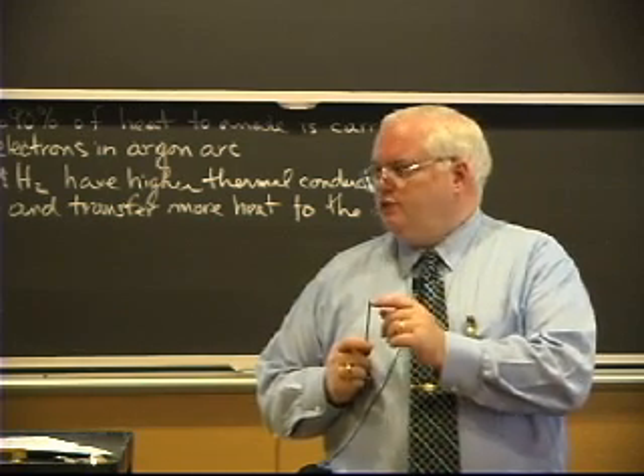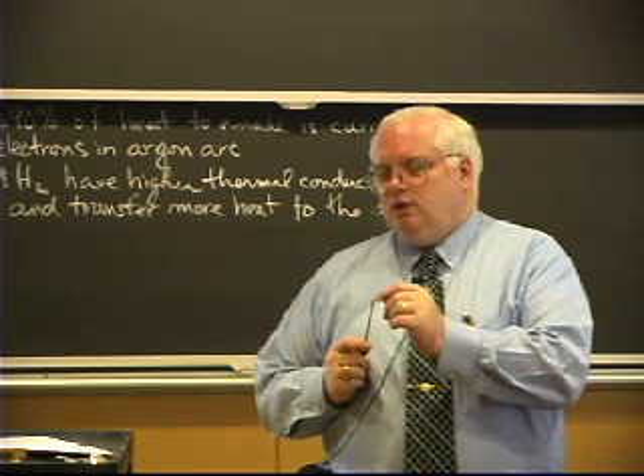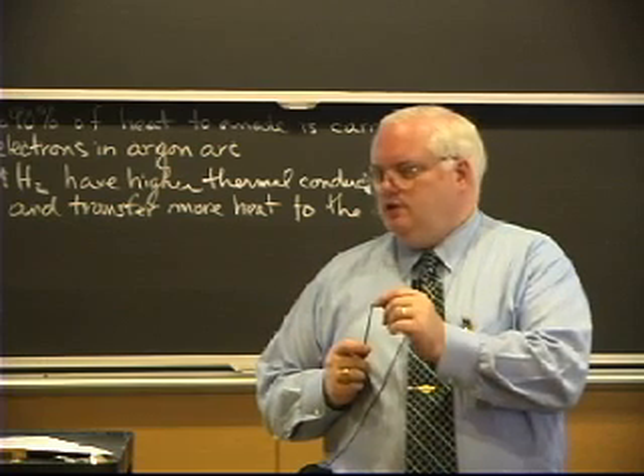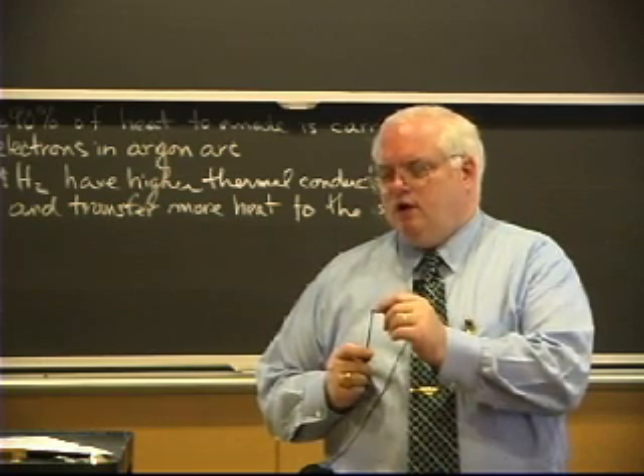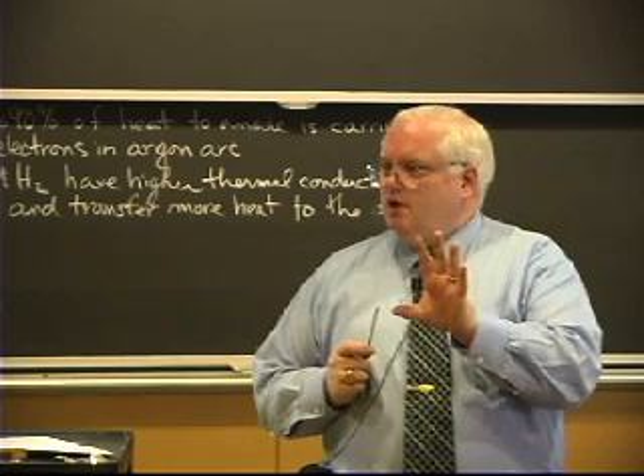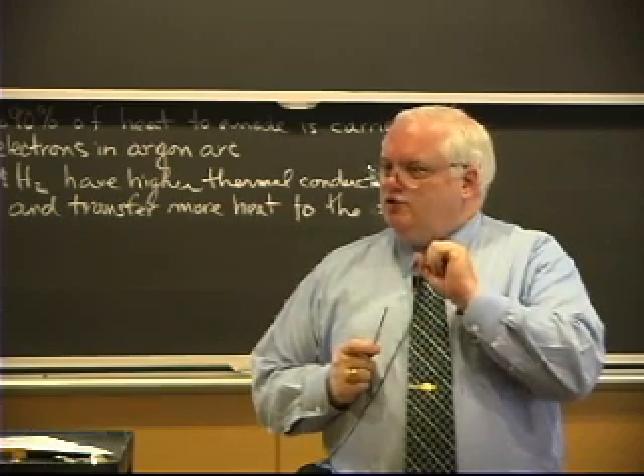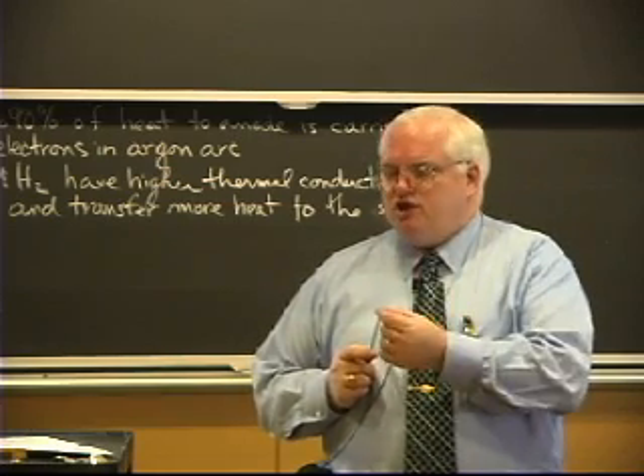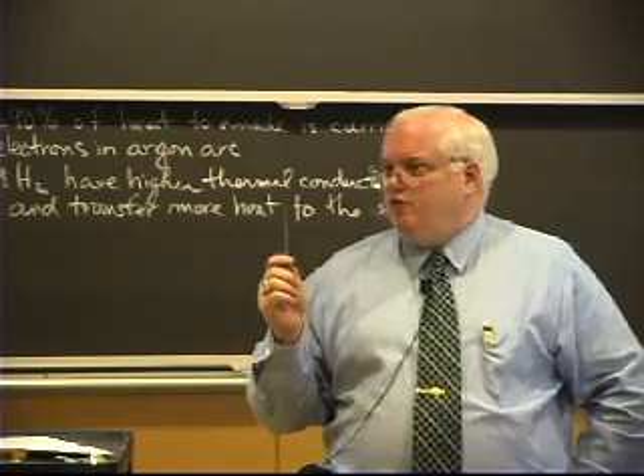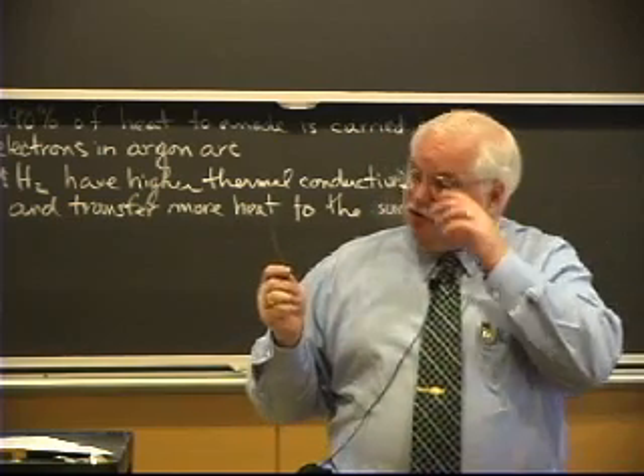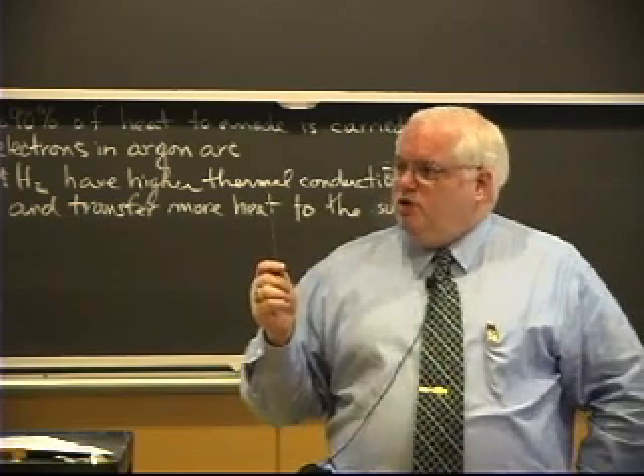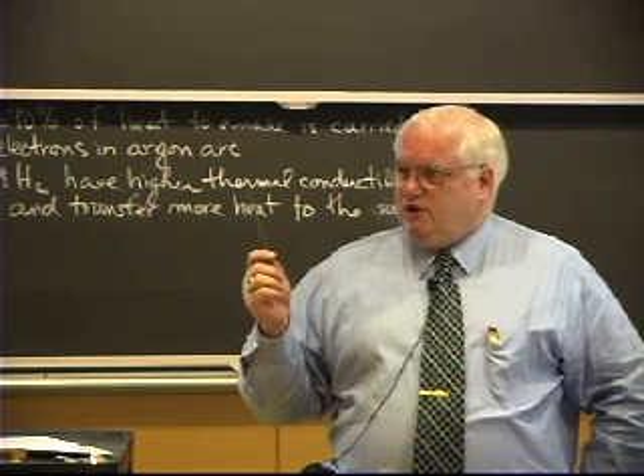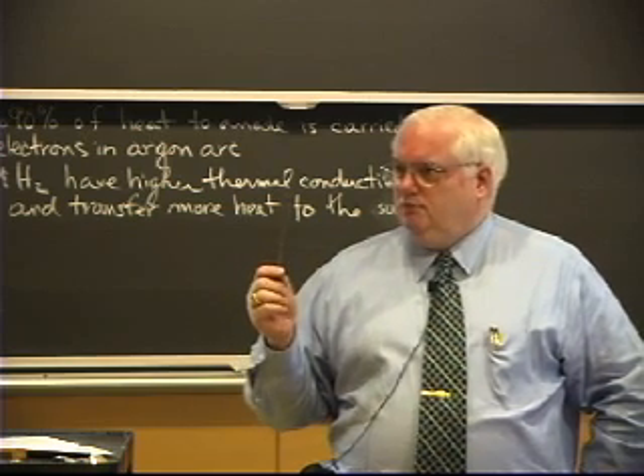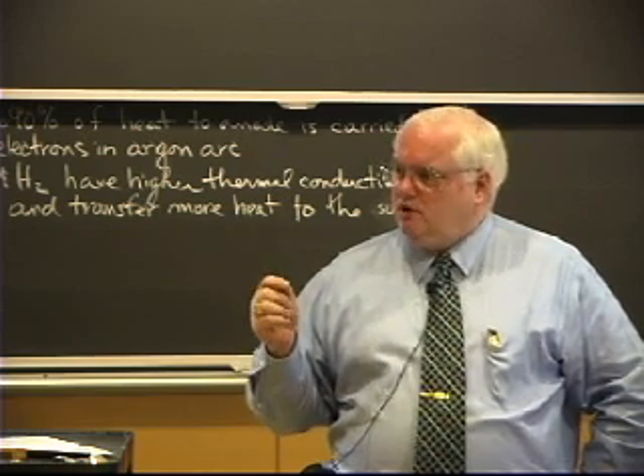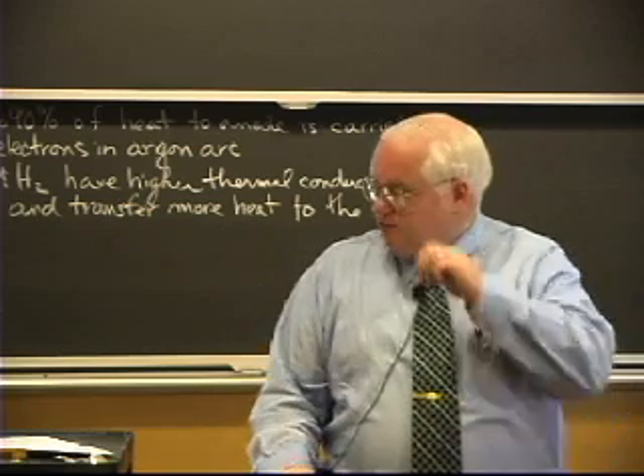If I put 2% thoria in there, those little spots of thoria will be where the electrons will come out, and there'll be only about a 2-volt drop. And so I actually generate less heat if I have a thoriated electrode. You can buy pure tungsten electrodes, but you're probably going to use 20% less current before you melt it. The thoria helps cool it because, again, it's easier electron emission.